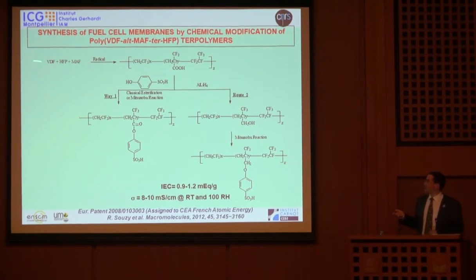So just to understand, from this, we obtain a material and we obtain a membrane. Recently it was patented by the Atomic Energy Commission and CNRS, and finally we got the authorization to publish, and we recently published this paper. So this enables some conductivity. The conductivity is not so high because at this stage it was necessary to blend with a commercially available PVDF compound in order to have good mechanical properties. But we are still working on that, even making block copolymers. Unfortunately, I cannot speak about that. And it seems that a better approach and higher conductivity are reached in this system.